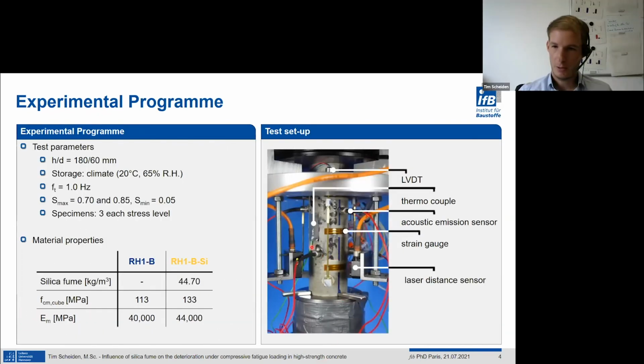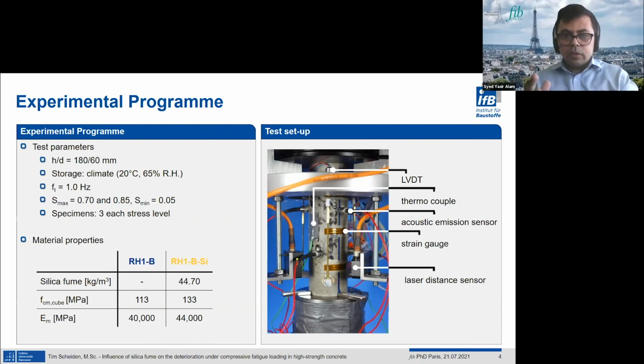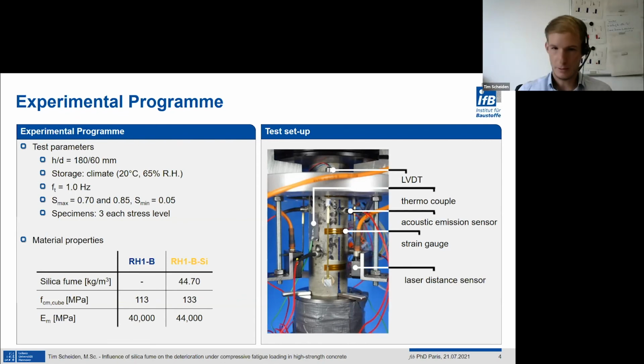Here we use wideband sensors, 6 attached on the specimen, 3 in the lower third, and 3 in the higher third, with a distance of 60 degrees. So we have the full 360 degrees. They are all equally spaced and symmetrical in their arrangement. Okay, because the cracking will not be symmetrical, just to make sure that the sensors collectively capture the same kind of activity in different tests. So it's good to have the same attachment for every test and test setup.